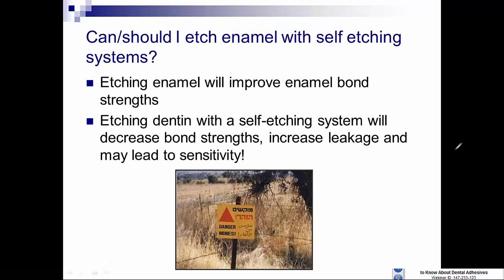Now, can you etch enamel with self-etching systems? And this is the selective etching system. Well, the answer is it will most definitely improve enamel bond strengths. However, products like Clearfil SE Bond, Clearfil S3 Bond, G-Bond have not been validated to have phosphoric acid leak onto the dentin. And in fact, SE Bond's dentin bond, which is excellent as a self-etching system, is reduced in half if it's applied to etched dentin. So selective etching or use of phosphoric acid with self-etching adhesives is in general contraindicated.